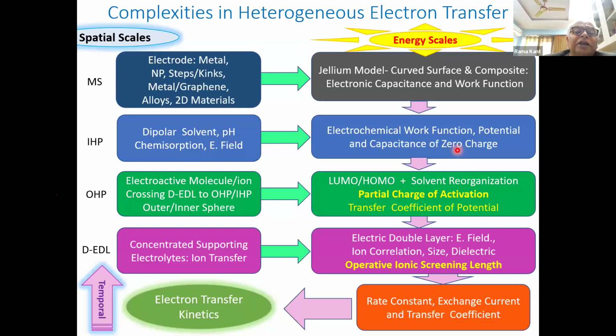The other is bulk. And here you have a metal, you can have a nanoparticle over it, which will complicate it, step skins over it, which will complicate it, put a 2-dimensional material, make alloys, all these possibilities you can have. How do we account for this in our model? We use a jellium approach with our own approximation. We are not using the standard jellium approach, but the physical idea is the same. And then we find the curved jellium work function or electronic capacity. Work function and electronic capacitance are related to each other. With that, we can play around with geometry and a lot of things, down to the atomic step level.